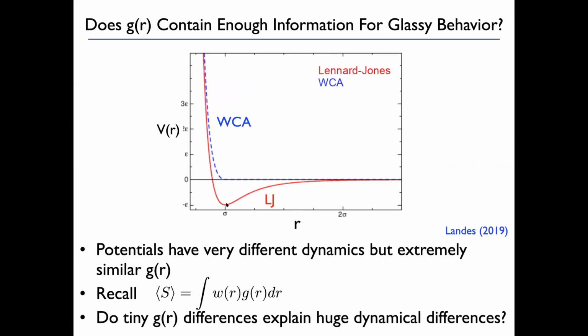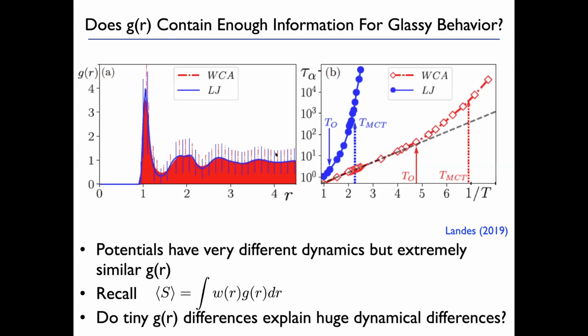And that is reflected in g(r). g(r) is extremely similar for these two systems, as the theory of liquids would say it should be. The repulsions make almost no difference to the pair correlation function. And yet, if you look at their dynamics, it's totally different. This is the relaxation time, tau. Sometimes I call it tau alpha and sometimes I call it tau, but they're the same thing. The relaxation time tau for the Leonard-Jones system looks like this, plotted as log of tau versus 1 over temperature. It shoots up. That's the blue one. And the system with only repulsions has a much more gradual increase of the relaxation time. So this tiny difference in the pair correlation function gives rise to a huge difference in relaxation time.